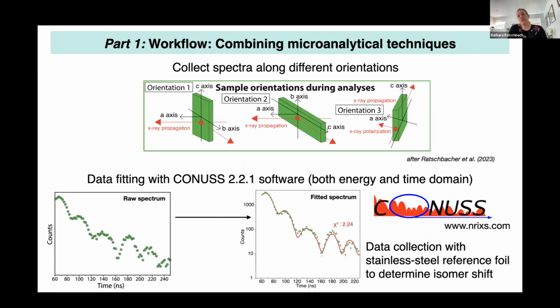So we also collect spectra along different orientations. So you can see that here in the first panel. And the reason we do that is because of the linear polarized nature of the synchrotron radiation and the polarization dependency of the hyperfine interaction at the iron nucleus. So by doing that, we analyzed at least 2 orientations for each individual grain we collected spectra on, and that really helps us to disentangle and discern between the contributions of crystallographically distinct ferrous and ferric sites in the amphibole structure.